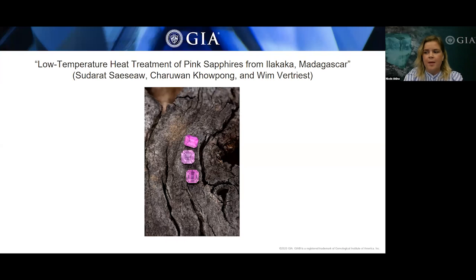But when heating corundum at much lower temperatures, it will only subtly affect the internal characteristics and inclusions, making the treatment more of a challenge to detect without advanced instrumentation. This article discusses the effect that these low temperature heat treatments have on inclusions and the FTIR, the infrared spectroscopy spectra, for pink sapphires from Madagascar.